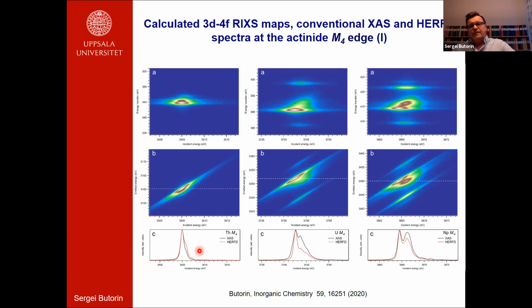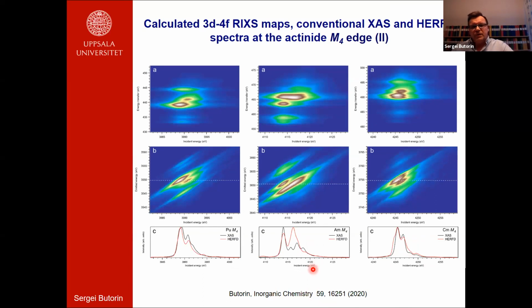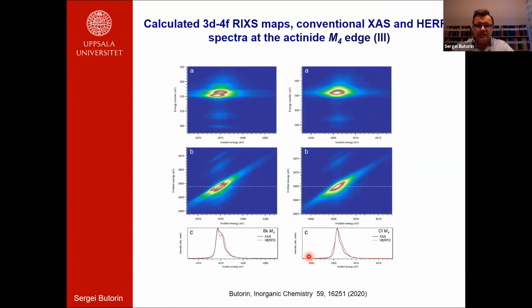As to the difference between HERFD spectra and XAS spectra at the M4 edge, we can see that the HERFD spectra actually reproduce all the structures of the XAS spectra, but the relative intensity can be different, for example here for uranium dioxide or for neptunium dioxide. The only large difference is found for americium here. Otherwise, they are okay. So it seems the overall agreement between XAS spectra and HERFD spectra is better for the M4 edges. So I would recommend using those edges in your studies.